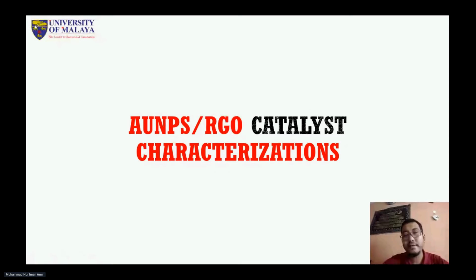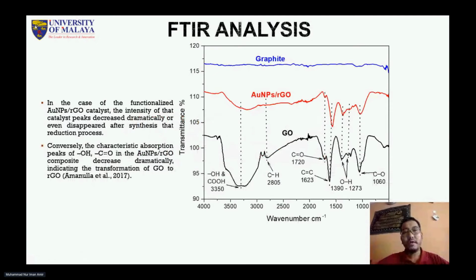Proceeding with catalyst characterization. What we can observe based on the FTIR analysis here is the comparison between graphite, the catalyst used for the reaction, and graphene oxide. So we can see the intensity of the catalyst decrease dramatically or even disappear after the synthesis process that undergoes the reduction process. So you can see the hydroxyl, carbonyl, and hydroxyl components decrease dramatically, which indicates the transformation of graphene oxide into reduced graphene oxide.